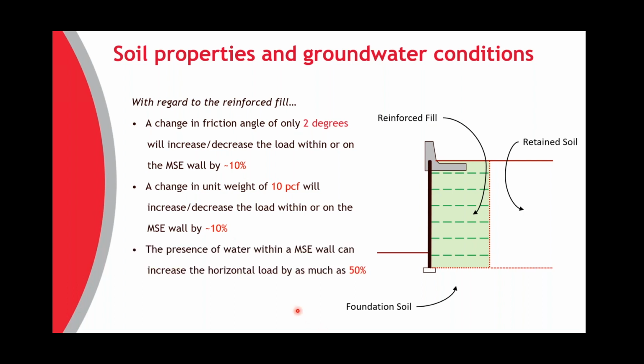But the presence of water can affect it by as much as 50%. That's why it is very, very important to keep water out of the reinforced zone. Most all failures of MSE type structures are generally the result of water, groundwater that it's not designed for, or inundated structures where you have a rapid drawdown type condition. So drainage is of utmost importance in the design of an MSE structure.